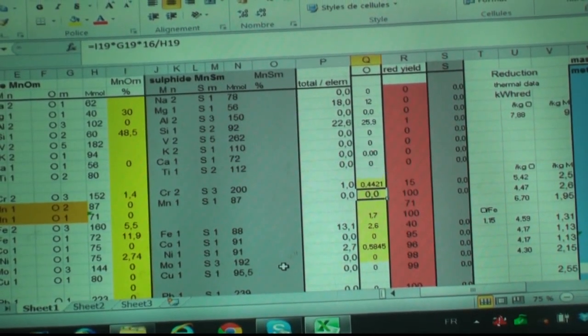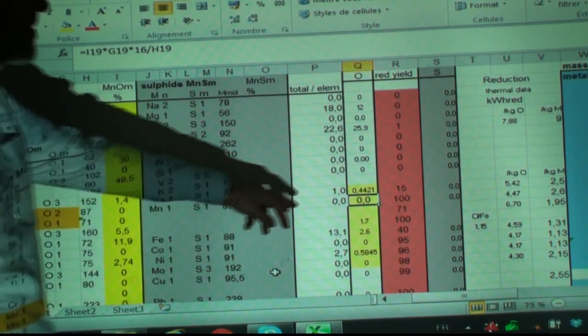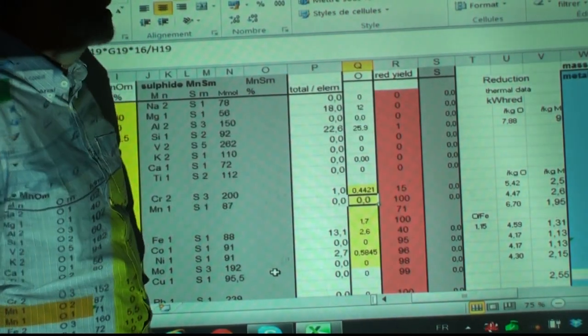In case of the high metal, they concentrate just on the reduction of the manganese. But for manganese too, they don't know the yield. They want to have about 30% manganese in the slag, because they have two products to sell. So they will adjust the carbon to have a good yield of manganese. Here it's the same: they adjust the carbon to have a good yield of iron. The other yields are really not so important.